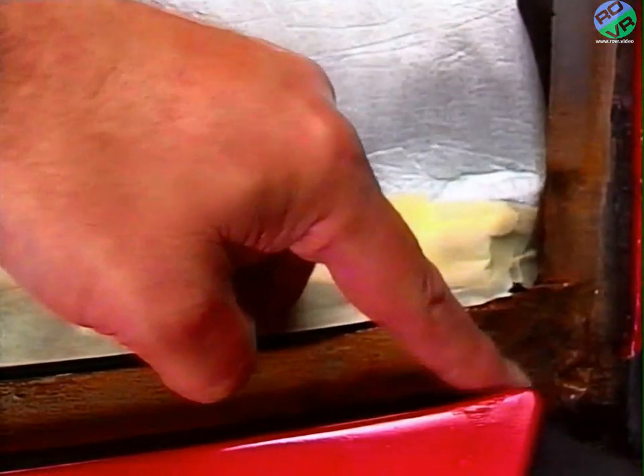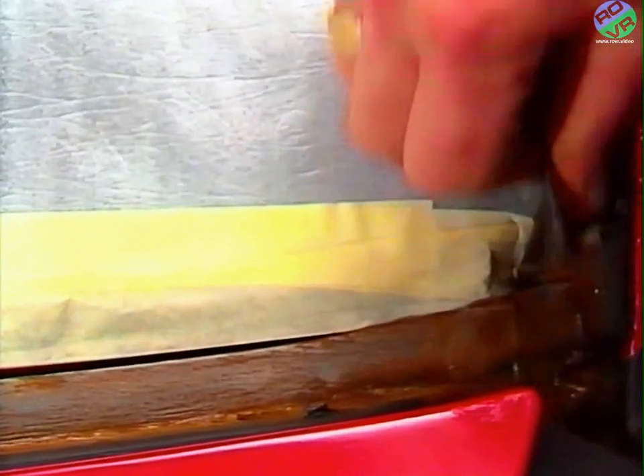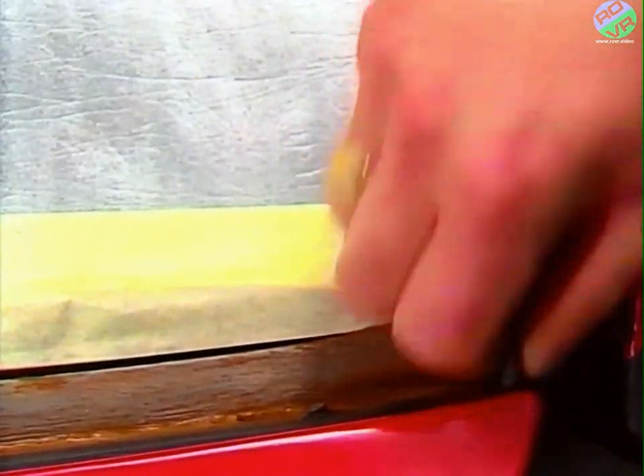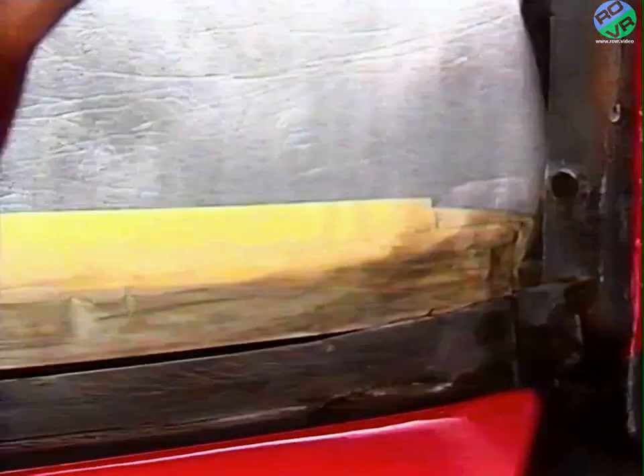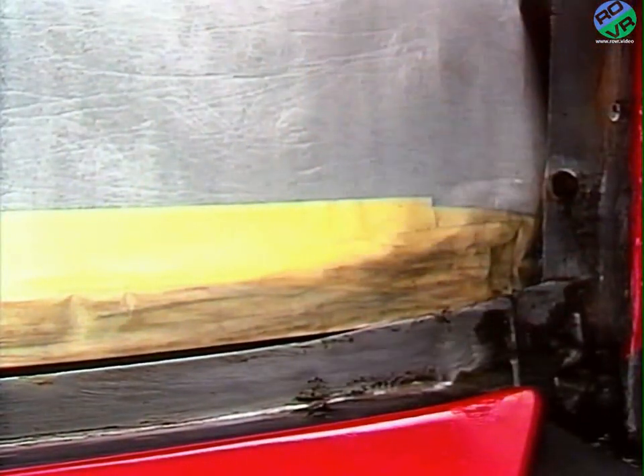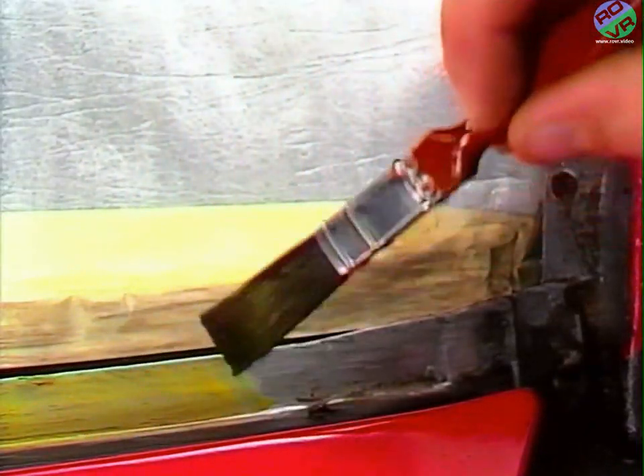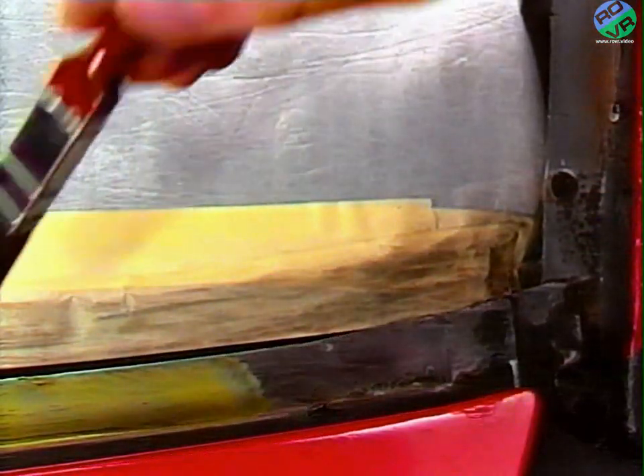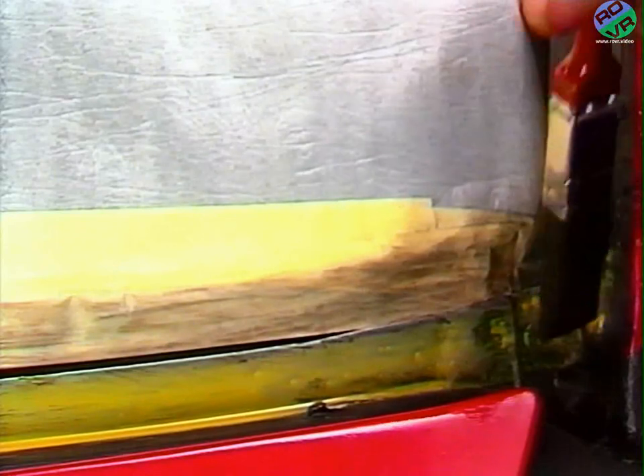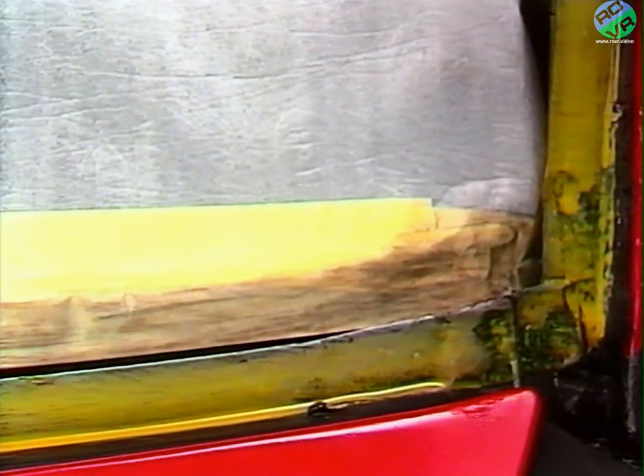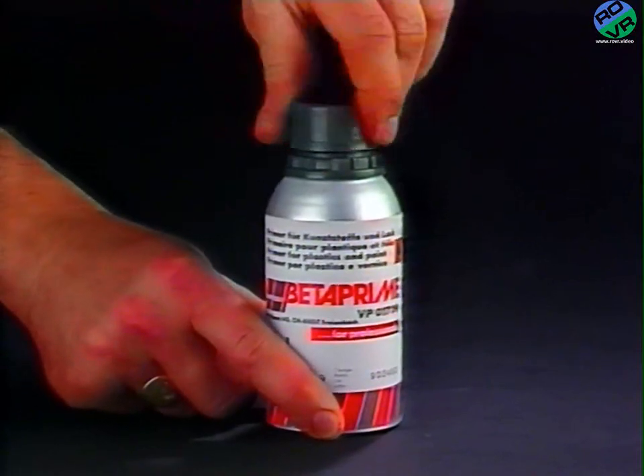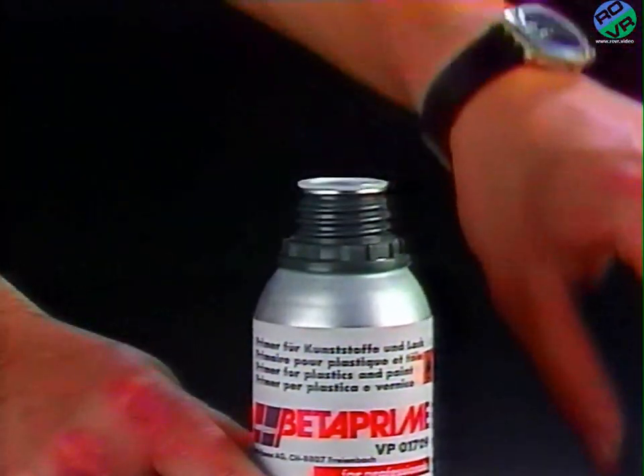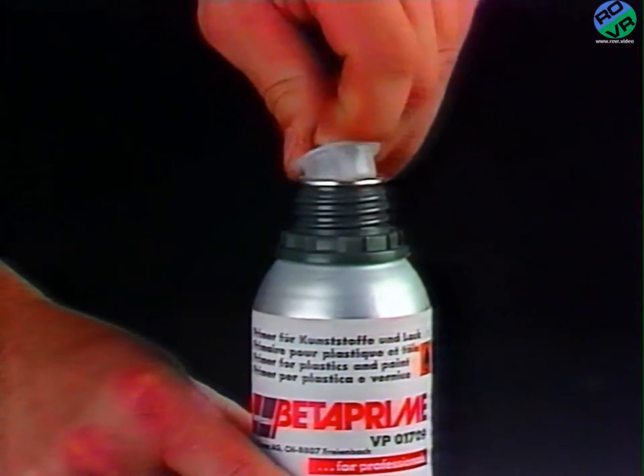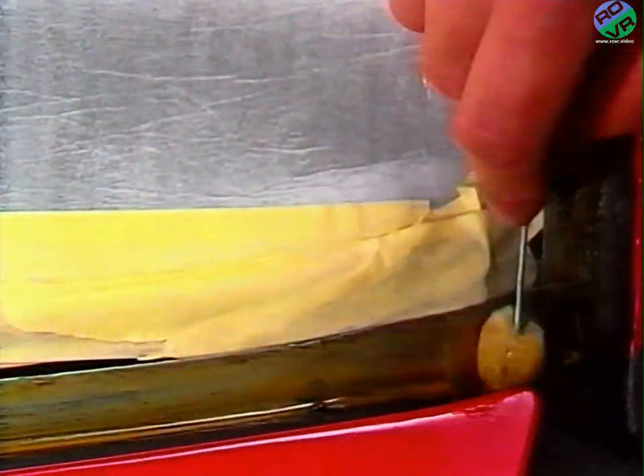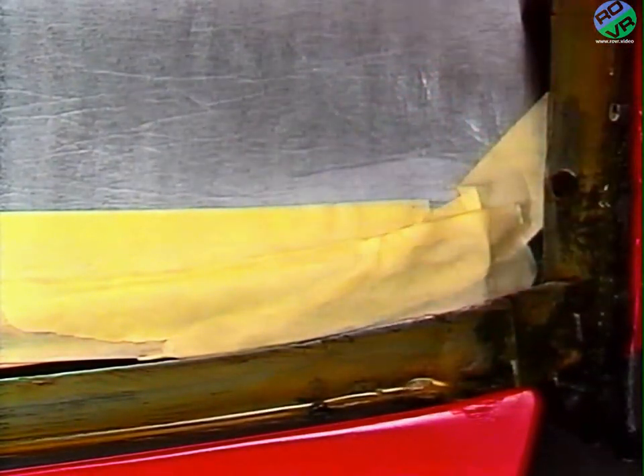Where the metal is rusty or corroded, first clean up the surface using wet and dry paper or some other abrasive. Then wipe on BetaClean 3100 cleaner and degreasant with a lint-free cloth. Now apply the pre-mixed Betaprime 1706 A+B with a brush, being careful to coat all the surface, and let it dry before the next stage. Now use the transparent VP 01709 primer accelerator from the grey pack with the grey cap. This product accelerates the cure between the 1706 A+B anti-corrosive primer and the new urethane.